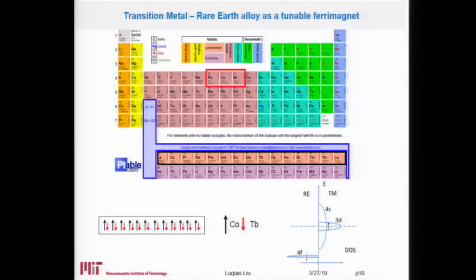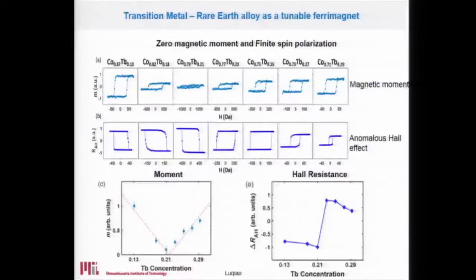So that's how you can reach a system that has almost zero moment, but at the same time has finite spin polarization. Actually, this is exactly what we observed in our experiment. So in our experiment, we make alloy out of cobalt-terbium with different composition. So from left to right, we have more and more terbium inside. So here we have 13% of terbium. Here we have 29% of terbium. As you can see, for a certain concentration, for example, here terbium about 21%, we get zero net magnetic moment. So this row is a magnetometry study which reflects the magnetic moment. As you can see, the magnetic moment reaches zero at certain concentration.